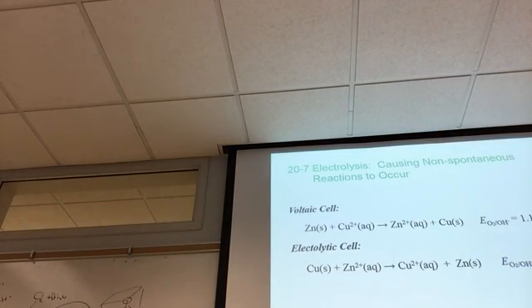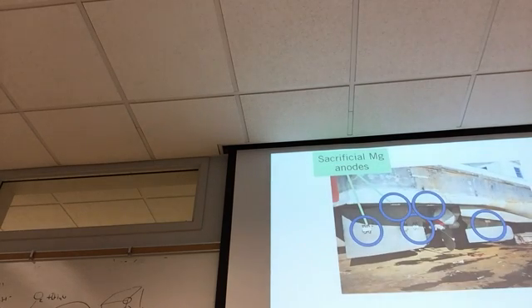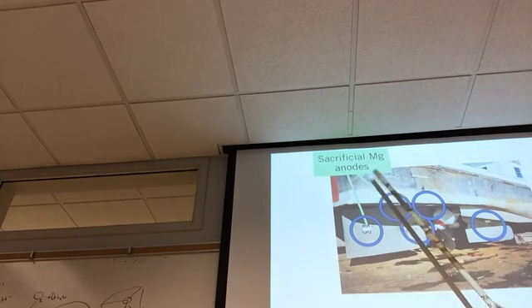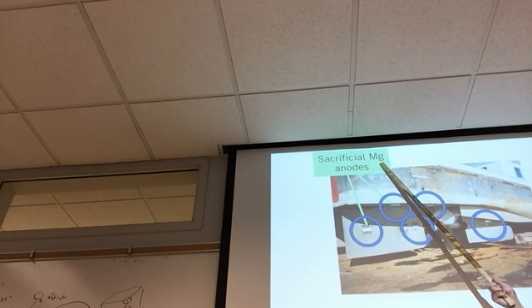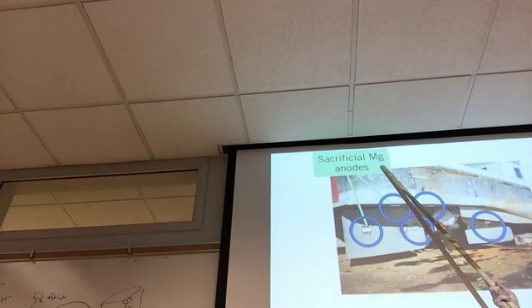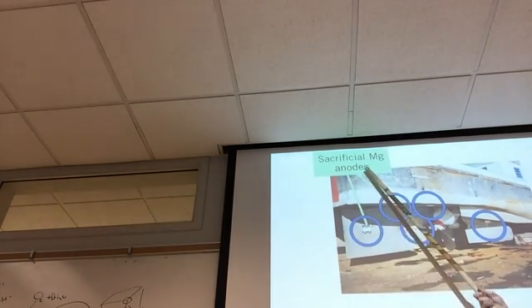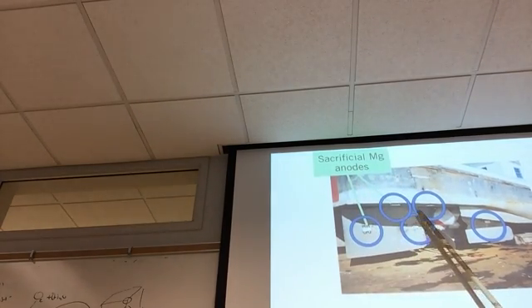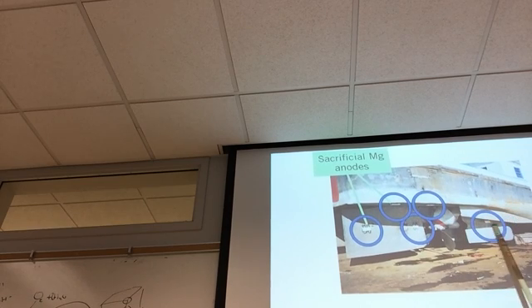Yeah, corrugated is usually made out of galvanized, I think. Recall, we don't have to use zinc, we could use magnesium. Magnesium has an even higher oxidation potential than zinc. And so here you can see sacrificial anodes of magnesium on a boat hull and rudders.